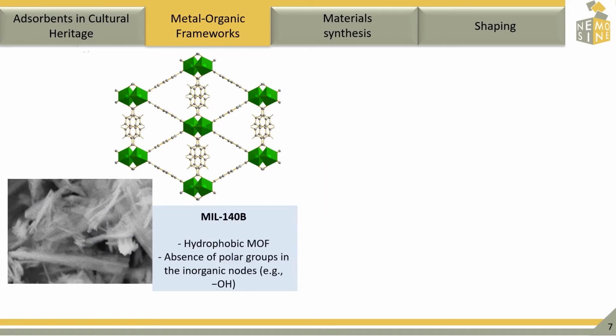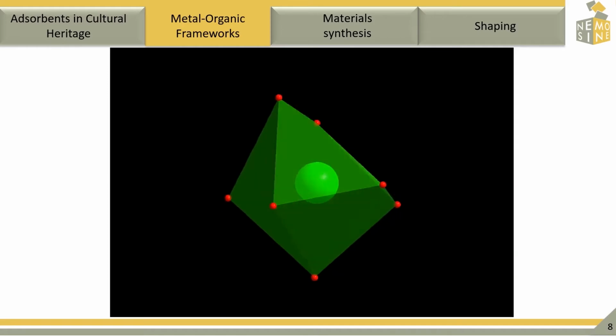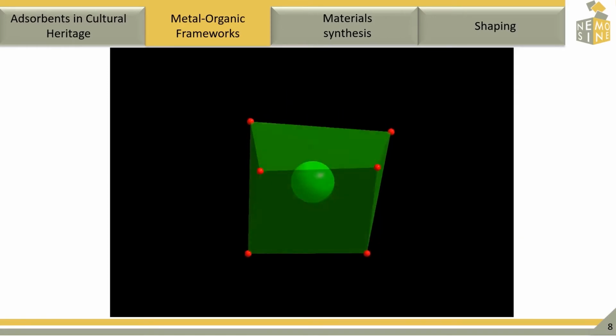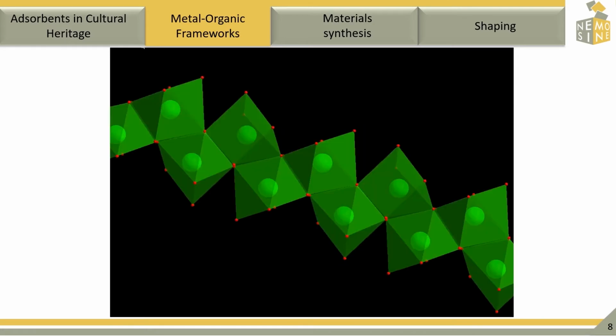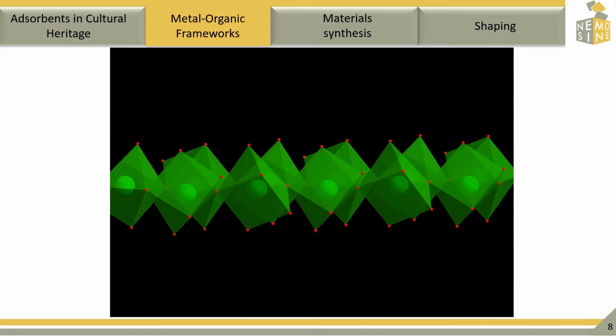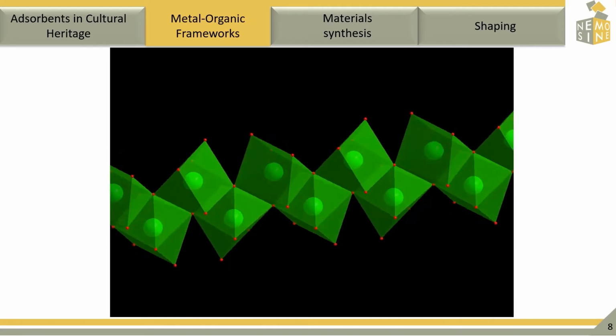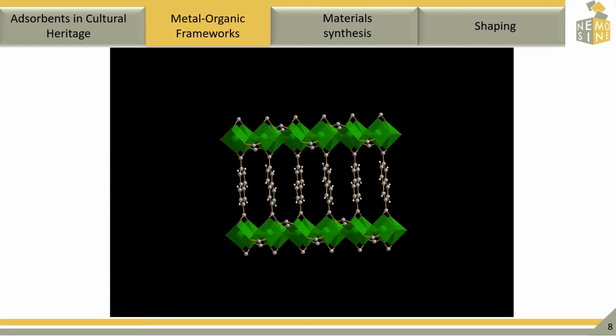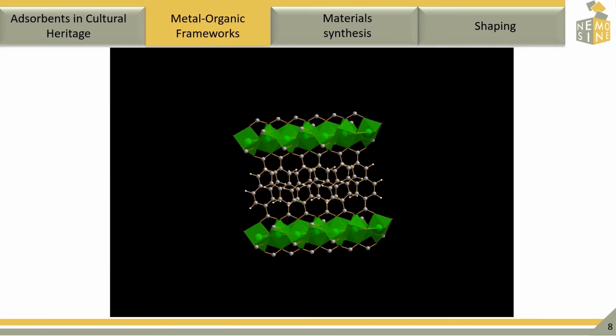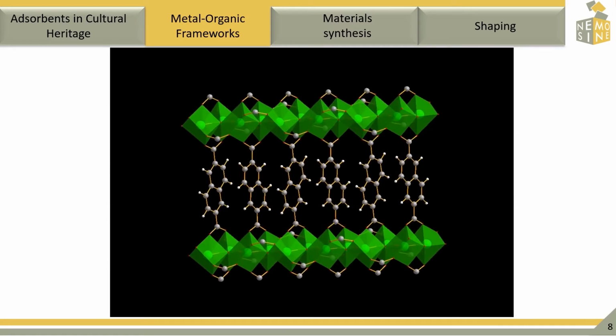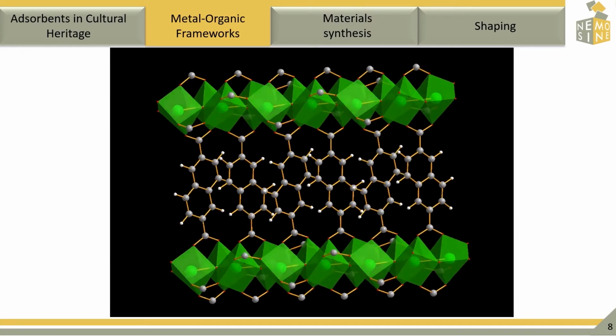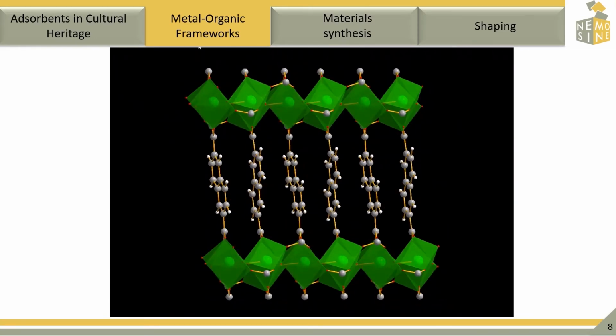For the purpose of conservation, initially two MOFs were found to be of interest. In this application, for example, MIL-140B, which is mainly a hydrophobic MOF, since it is absent of polar groups in its inorganic nodes. As you can see here, it is built from oxo clusters of zirconium that are connected to each other and form a chain, and this chain is then connected to another chain by the aromatic dicarboxylic ligands, delimiting 1D triangle channels that you can see in this animation.